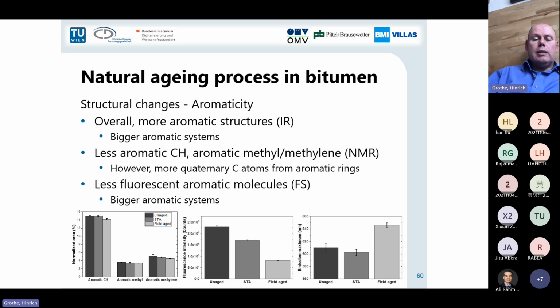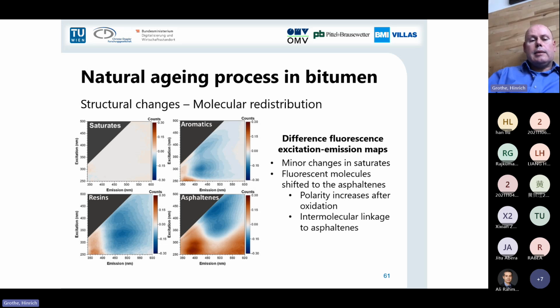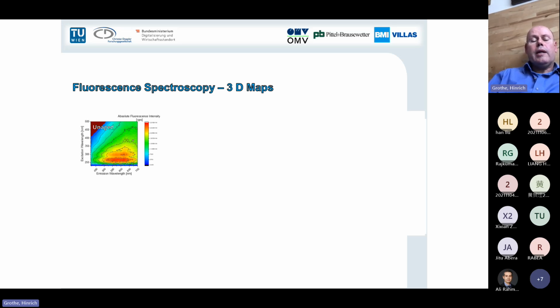So to summarize that a little bit, as I said, in the NMR we observe a little bit different things than in the infrared in terms of the aromaticity. And we tried to figure that out using also fluorescence. And fluorescence shows us again that we have a shift in the asphaltenes. And of course, the polarity is increasing, the oxygen is taken up. You have intermolecular linkage to the asphaltenes, and we can then compare also those results gathered with a fluorescence mapping here with lab experiments and with field experiments.